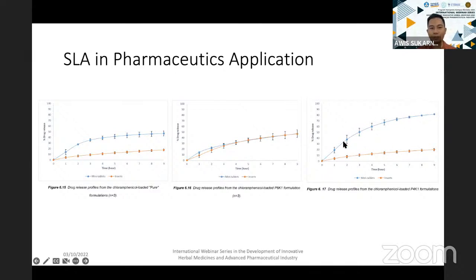Again, this is because for the insert, for the PEG 6000, it showed a very smooth release profile, but for the mini tablet, because it breaks into smaller pieces, that's why at that point it released faster compared to the insert.